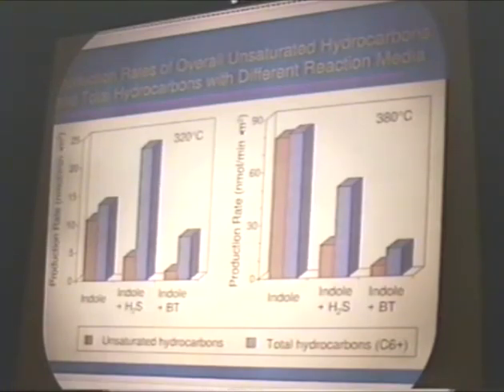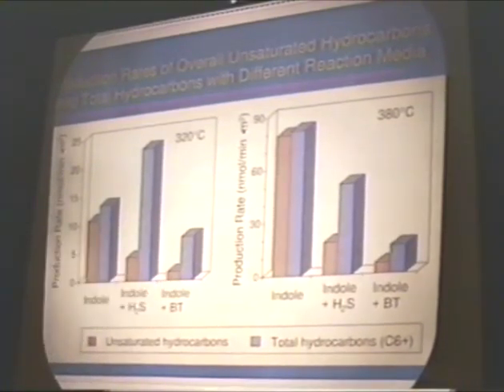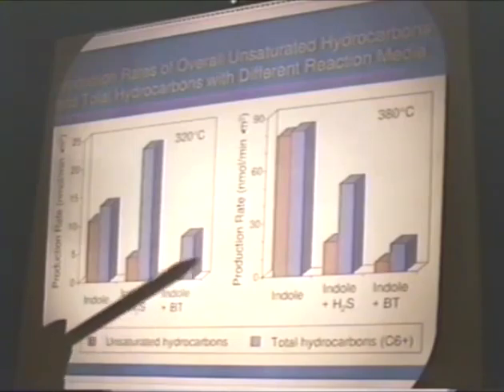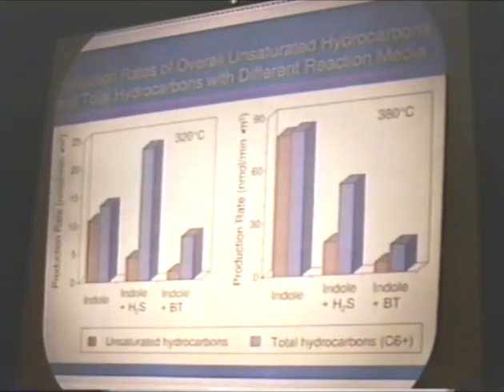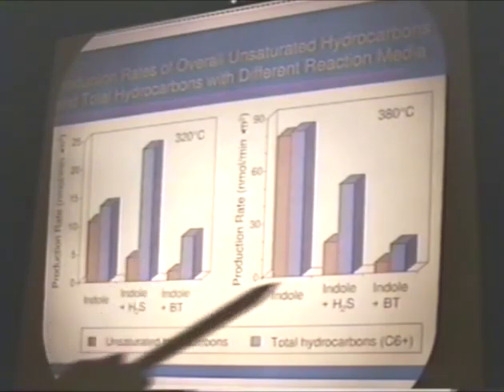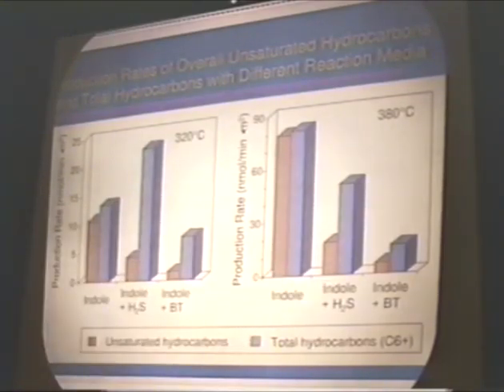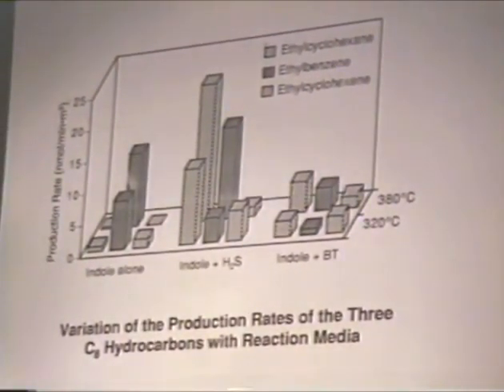this point. Now, if we introduce a sulfur compound to the system, well, first of all, with the benzothiophene, there is an overall inhibition effect, but maybe more importantly, if you compare the blue bars with the pink bars, we will see that the aromatics, the unsaturated hydrocarbons, this time really make up only a small fraction of the total hydrocarbons, meaning the majority of the hydrocarbons that we are producing are completely hydrogenated in the presence of sulfur compounds.